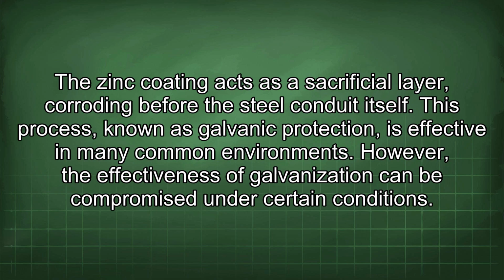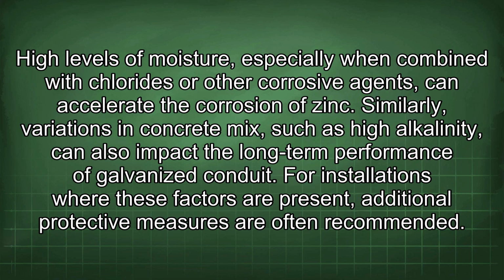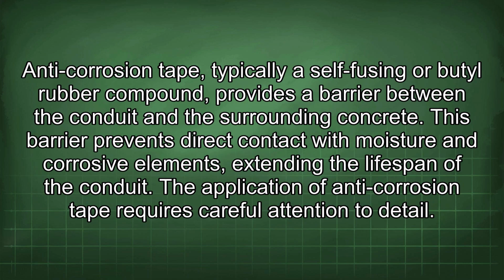However, the effectiveness of galvanization can be compromised under certain conditions. High levels of moisture, especially when combined with chlorides or other corrosive agents, can accelerate the corrosion of zinc. Similarly, variations in concrete mix, such as high alkalinity, can also impact the long-term performance of galvanized conduit. For installations where these factors are present, additional protective measures are often recommended. Anti-corrosion tape, typically a self-fusing or butyl rubber compound, provides a barrier between the conduit and the surrounding concrete. This barrier prevents direct contact with moisture and corrosive elements, extending the lifespan of the conduit.